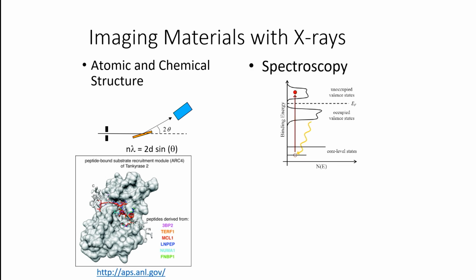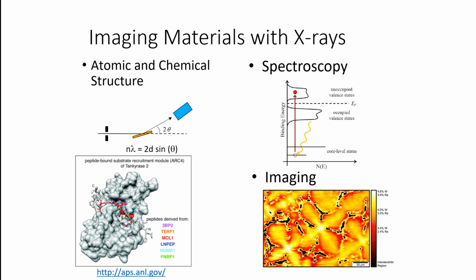The other thing you can do with X-rays, particularly if you go to an X-ray source like the one that Sean runs now, and Ken, is that you can tune the energy of the X-rays to excite transitions in your material. So you can get really specific chemical information about your system. I'm going to talk about how we can also use this X-ray spectroscopy to get information about the spin, the magnetic properties of the individual elements in the materials that we fabricate.